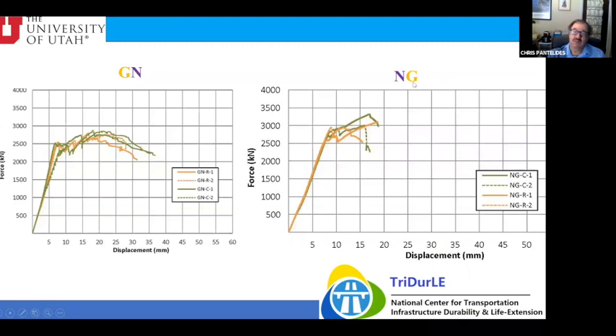So here's one with the fiberglass spiral and the stainless steel vertical. And again, you can see that the corroded have a little bit less capacity than the control. But the definite thing you see here is that the axial displacement is significantly less, almost half, compared to the specimen with the stainless steel spiral. And we expected this because the stainless steel spiral has a much higher tensile strain capacity than the fiberglass spiral.